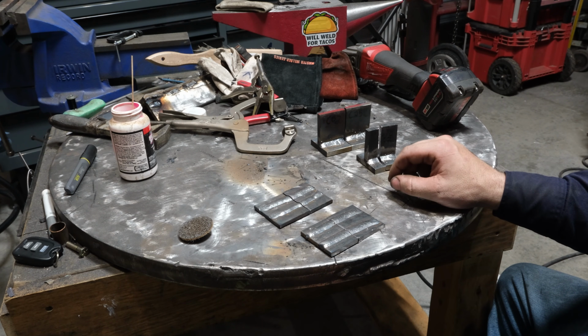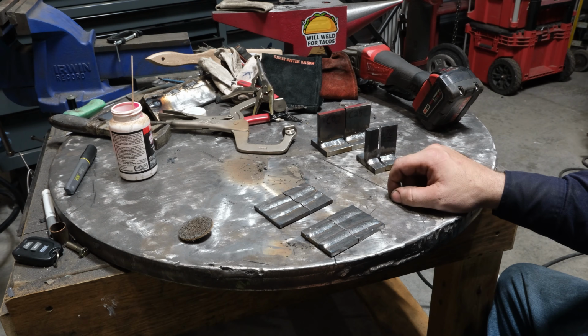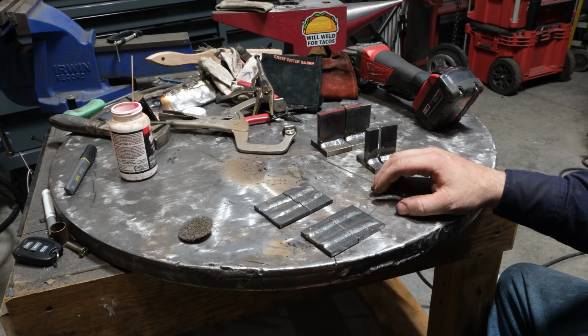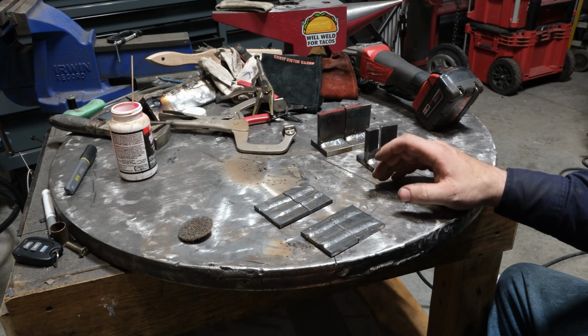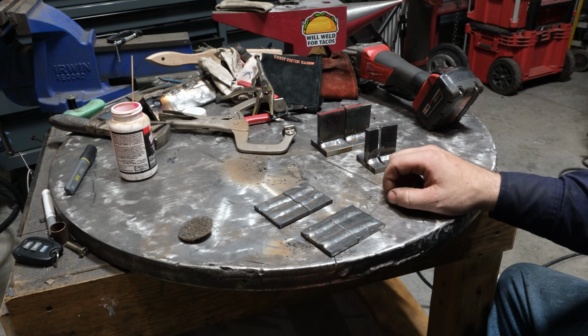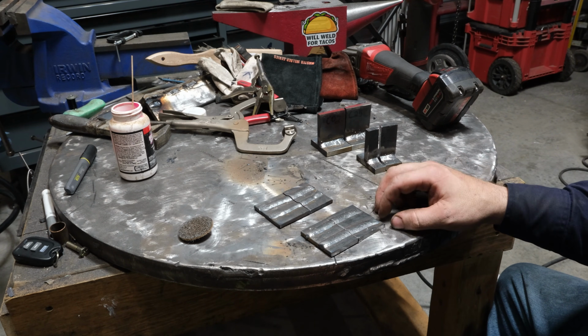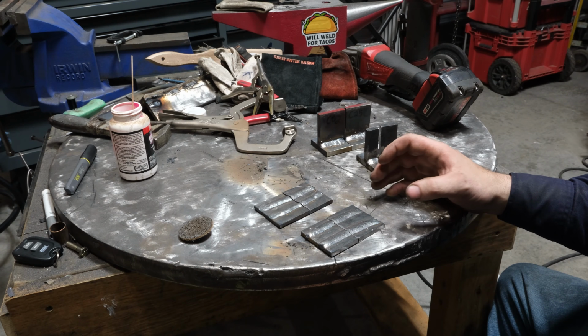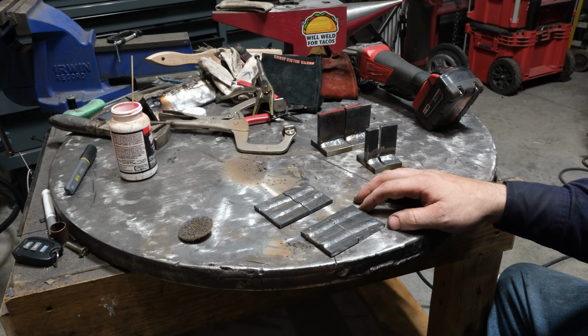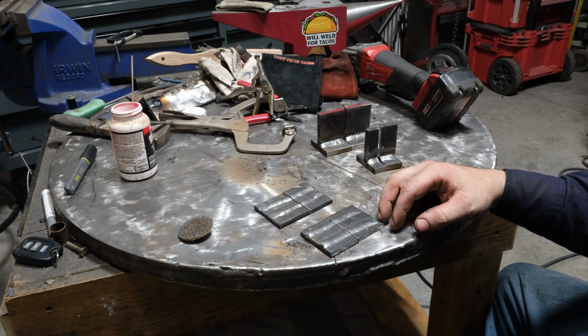The chart that I had for this through ESAB had a little disclaimer at the bottom that said reduce voltage for C25 by a volt, volt and a half. Well, I didn't lower it by that much, therefore a combination of likely too short of a stick out and a little bit too high a voltage, we got some surface wormholes. Not a big deal. It's not really going to affect the penetration any, so just so you know, that's there.